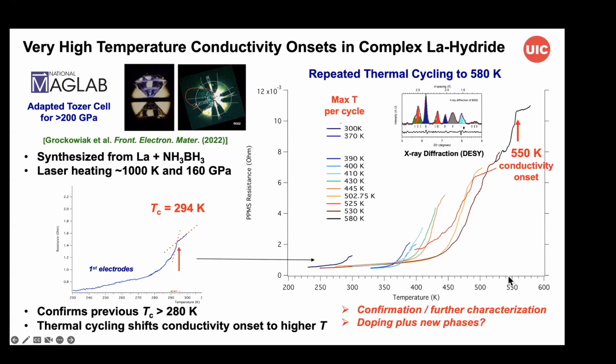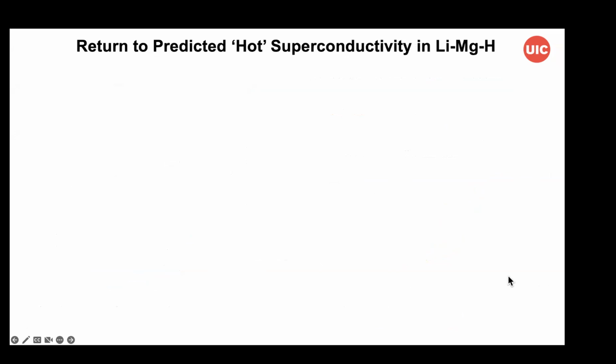And as you probably heard, when this was cycled repeatedly, thermally, increasing thermal cycling, cooling, and warming, this onset shifted to much higher values. So evidence for a conductivity onset above 500 Kelvin. Whether this is superconductivity remains to be proven. This was only one experiment that was cut short by COVID. Some diffraction measurements were done that are in support of the idea that we still have a lanthanum-based material, but clearly more work needs to be done to determine whether this is truly hot superconductivity.